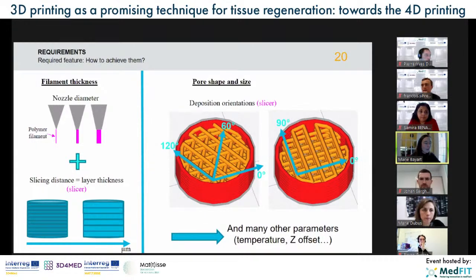Then for the filament thickness, you can adapt different nozzle diameters. For example, for the freeformer, we have 3 different nozzle diameters. So you may think we will choose the smallest one, but we have to keep in mind that we are using particles, and we don't want to clog the nozzle. So maybe we needed to choose a slightly higher diameter one. So we chose 200 micrometers.